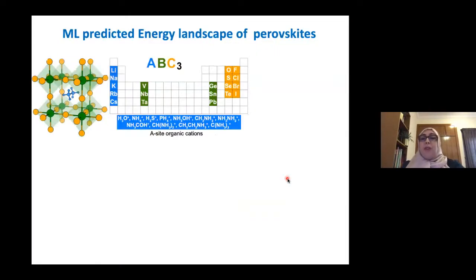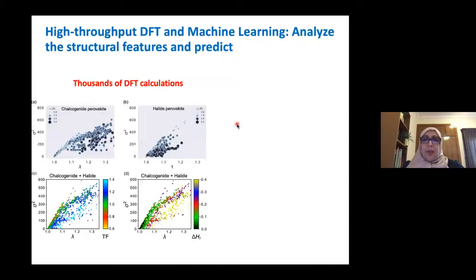And then we took it further, it was such a success that we moved from very simple cation to larger cation and organic cation, which was also a challenge. And then we built a database of all these calculations that you see here. So this has resulted in thousands of DFT calculations, both in halide perovskite and chalcogenide perovskite. And here I'm displaying the graph showing the distortion of the octahedra that are composing the perovskites. And this correlates very tightly with their intrinsic stability.